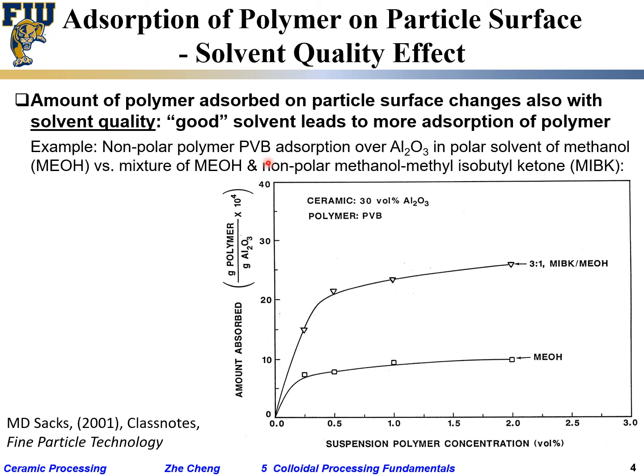Okay, so this is related to the solvent quality, because for PVB, this type of non-polar polymer, the more polar solvent would be a so-called, quote-unquote, bad solvent. Within methanol, it does not really want to stretch out. It does not want to interact with the solvent. On the other hand, the less polar solvent, MIBK, is closer to my PVB polymer. So they like each other. The polymer stretches out more, spreads out more, instead of coiling together, becoming a bead, or having something like phase separation. Here it's more uniformly dissolved.